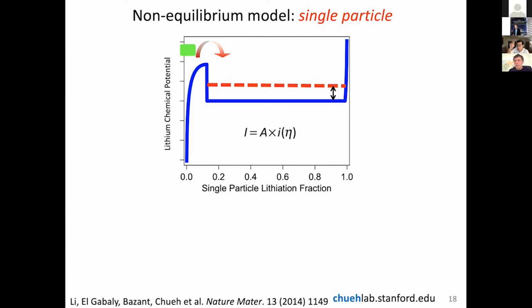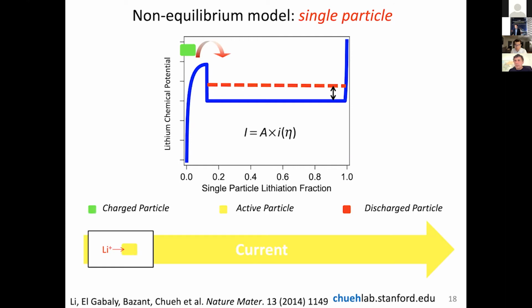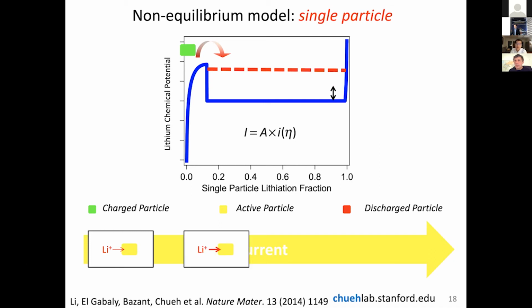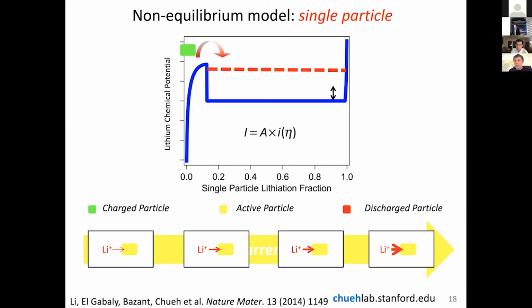So you basically trace over the blue line. So initially, you are inserting lithium, and as you ramp up your current, you're increasing your driving force. So you need to raise the red line a bit, but you will still follow the shape of the particle. So the current will get higher and higher and higher for your single particle. So here the width of the arrow represents the magnitude of the current. But what happens when you have many particles?